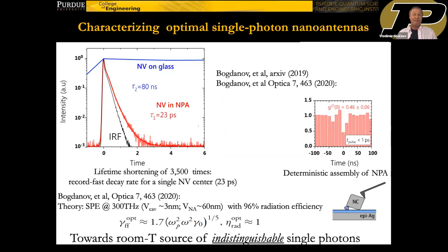Specifically, what we obtain is a lifetime shortening of 3,500 times. And also we obtained a record fast decay rate for a single nitrogen vacancy, which was as short as 23 picoseconds. We checked that it's indeed a single photon source by measuring this G2 correlation function. And as our theory shows, if you further optimize this system, these are the numbers we would like to have, like the size of the cavity should be really small, like 3 nanometers. For this, of course, we probably would prefer to use not nanodiamonds, but rather something like a 2D material, like hBN, which does have good single photon sources in defects.